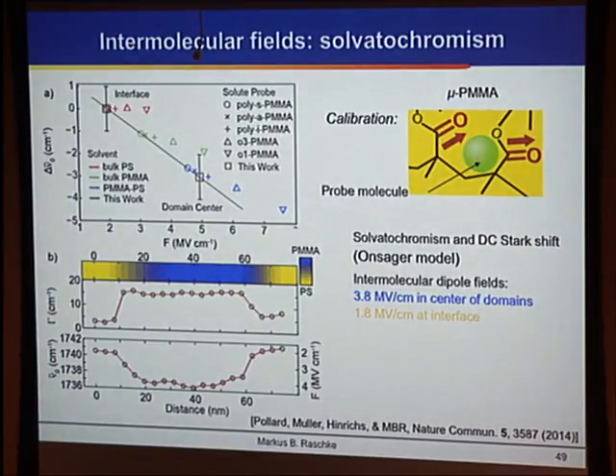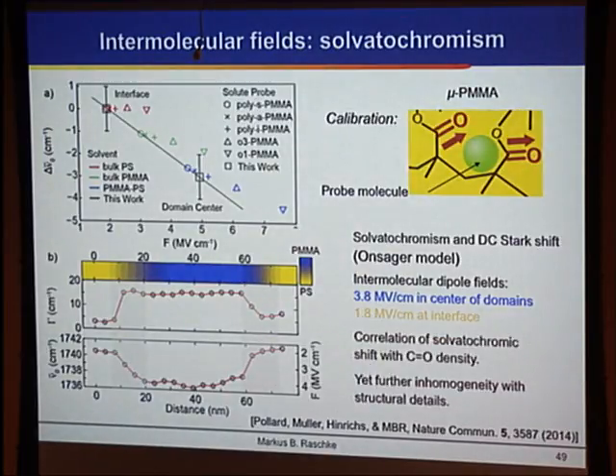So really, between molecules, there are gigantic local fields, and this is why it's no surprise how extremely sensitive a lot of biological processes are to activation potentials and to certain salt concentrations, and also in organic photovoltaic systems, how extremely sensitive one is to molecular orientation at these interfaces, which control exactly these field processes. And this is really the first time we were able to get a microscopic view of the distances and magnitudes of these local fields over these very short length scales.